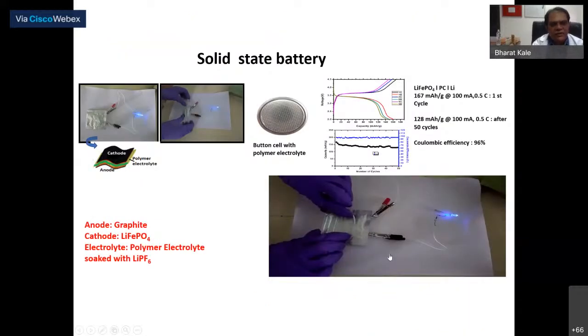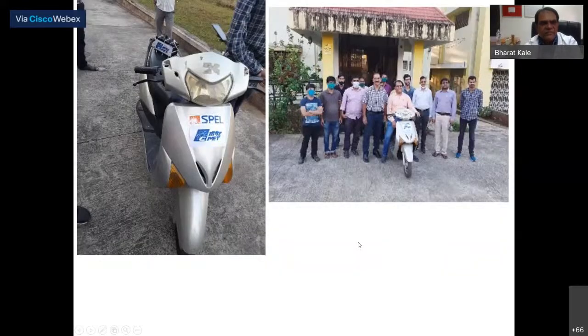Then we also made a solid state battery. We have made a polymer electrolyte. Generally in the market now we have only organic electrolyte, and because of that organic electrolyte, we cannot charge the batteries fast. Now we are working on the solid state electrolyte so that we can charge the batteries fast. So this is one of the electrolytes we have used, and we found that we get good capacity, around 128 milliamp-hours per gram. Now we are working on the stability of this electrolyte.